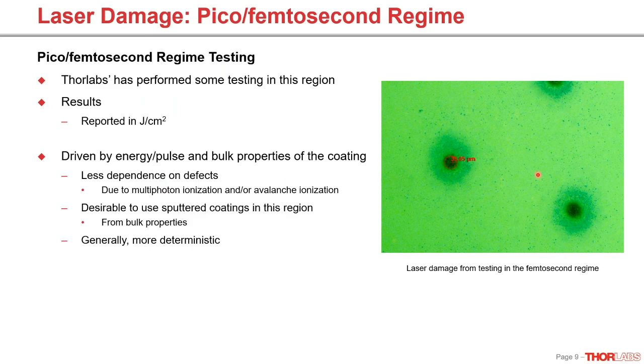So one interesting thing about the ultrafast regime is that damage threshold is driven less by defects, although obviously defects are a concern, and more about the intrinsic properties of the coating. So basically, you want your coating to resemble the bulk material as much as possible, as if the coating itself was a bulk material. So you want to use something that's going to give you a thick, robust film. So you tend to get better results in this region if you use sputtering, whether that's ion beam or magnetron. And this tends to be a little more deterministic because of that, which is nice, because we would rather have a deterministic than a stochastic process in this instance. So next, let's look at the mechanisms.